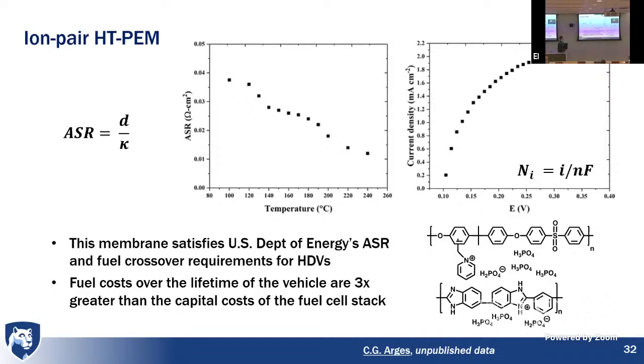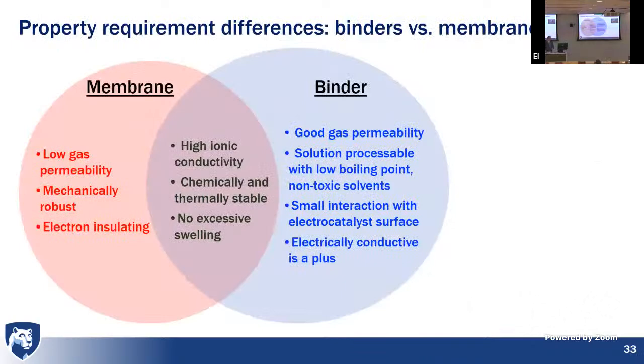And then the hydrogen crossover is really low. It's about 2 milliamps per centimeter squared. So you can back calculate that into a hydrogen crossover. And that's important in the heavy duty vehicle area because the fuel cost for the heavy duty transportation is 3 times higher than the capital cost of the fuel cell stack. So I want you to think about the membrane and binder chemistry a little bit.